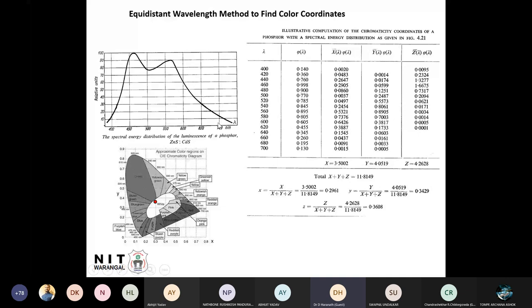Some typical household spectrum I have taken, and we have to normalize it to 100%, that is 1. The highest peak will be 1, and accordingly the intensity numbers will change for all wavelengths. Here I have taken a difference of 20 nanometers from 400 to 700: 400, 420, 440 nanometers. For every wavelength, what is the intensity? This phi lambda is the intensity. At 400, this is the intensity value.